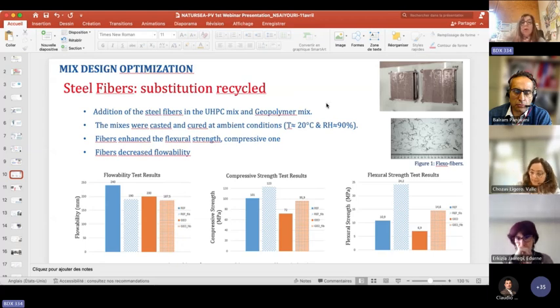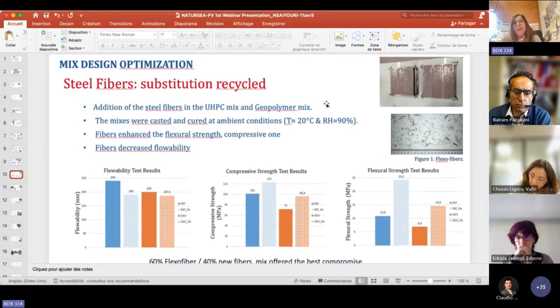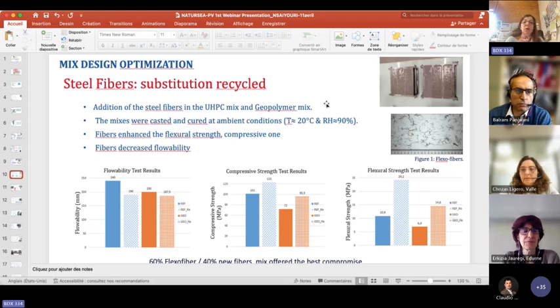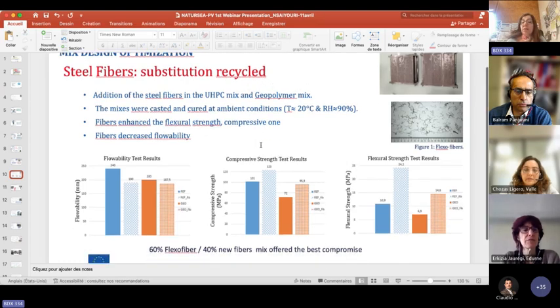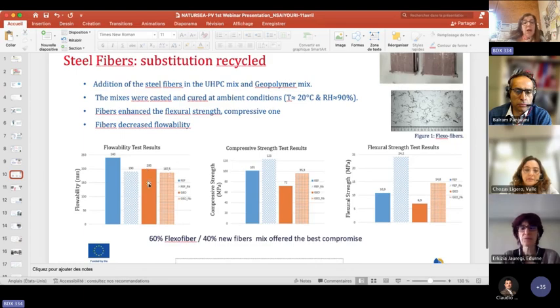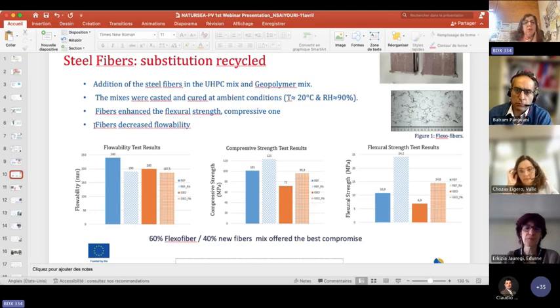We have another parameter we work on, which is steel fibers. Here we have two. I will not go into all the details, but I can mention that we use new steel fibers and also recycled steel fibers, and that allows us to have results for flowability and compressive strength. We obtained a decrease of flowability with fibers, which is an expected result, and fibers enhance the flexural strength and also the compressive strength for all mixes.